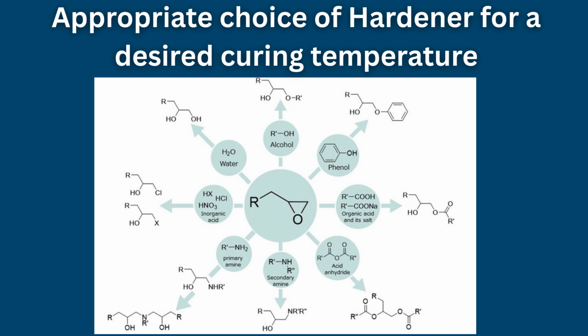Flexibility in epoxy systems can also be enhanced by adjusting the stoichiometric ratio of resin to curing agent. For instance, changing the curing agent from a rigid anhydride such as hexahydrophthalic anhydride to a more flexible amine-based curing agent can significantly improve the impact resistance and elongation at break of the resulting polymer.